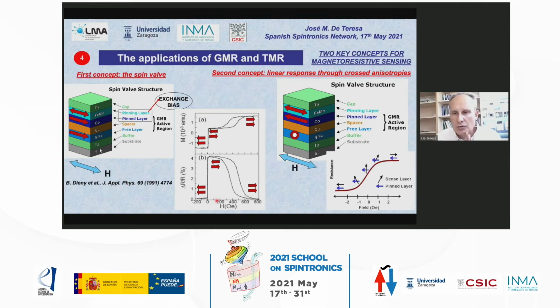But I want to mention two key concepts that helped to develop this magnetoresistive sensing. Without them, probably the technology would not have been successful. The first one was the concept of the spin valve. If you remember, when I showed the results of Grünberg and Fert, these were layers with two configurations of different resistance, but in sensing, it's better if you have a sensor with a linear response at low field, and this linear response is as high as possible. This was obtained with the spin valve concept and the cross anisotropy concept.